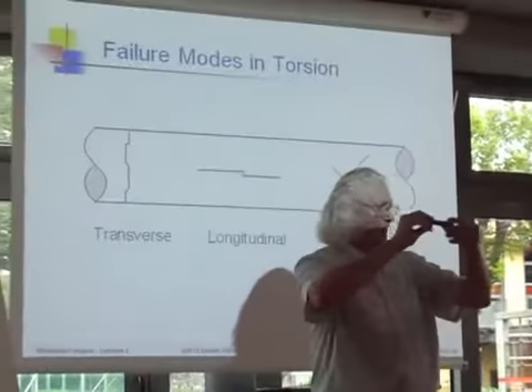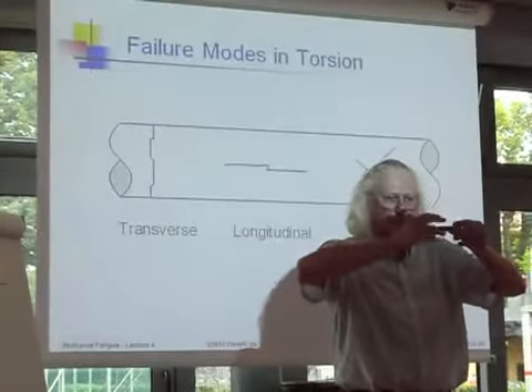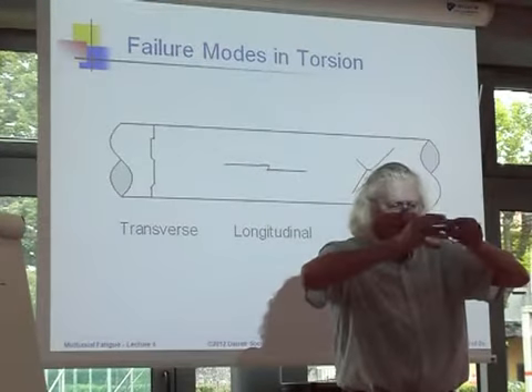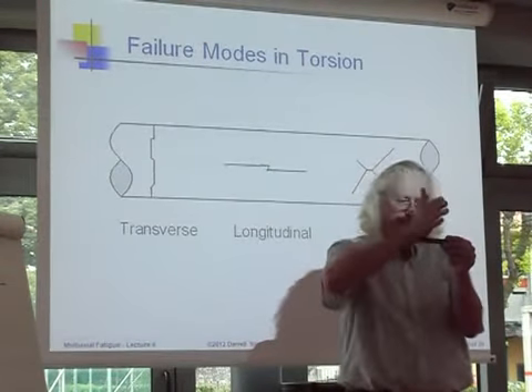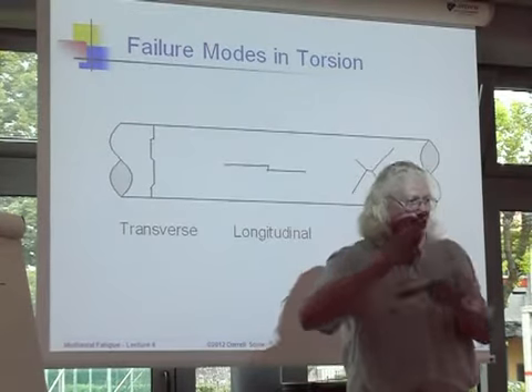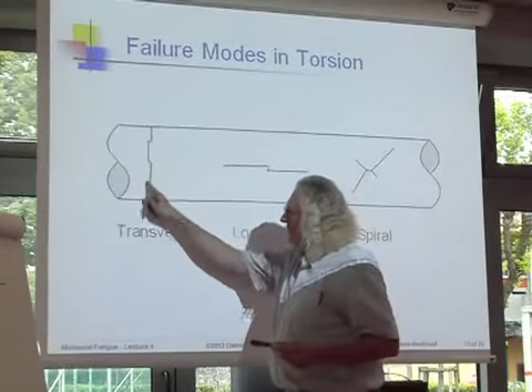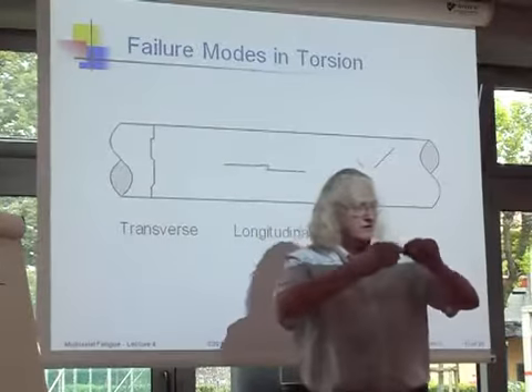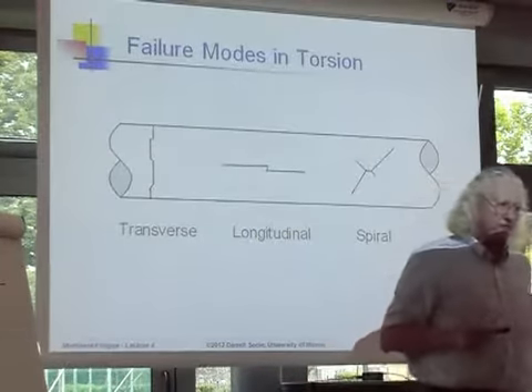If you test something at a very high stress level, not very many cycles, right? So I just twist this and so on, not very many cycles, then the failures are always transverse. They start and they just grow across the specimen like this, just like a static failure in twisting.